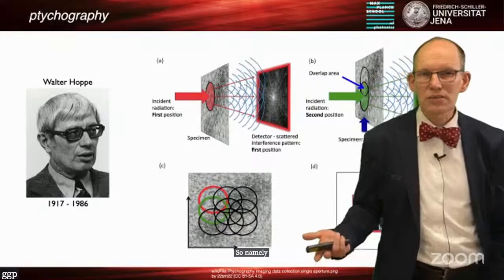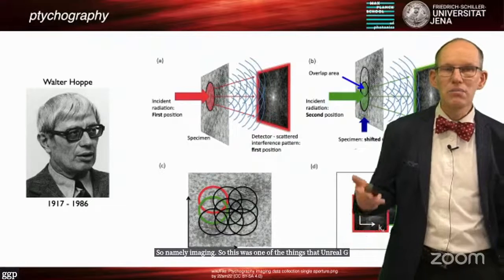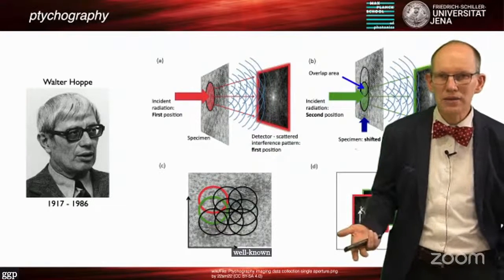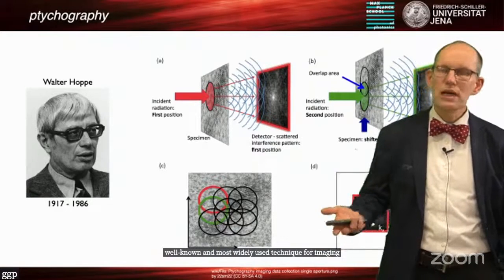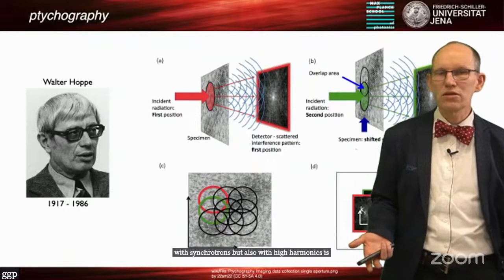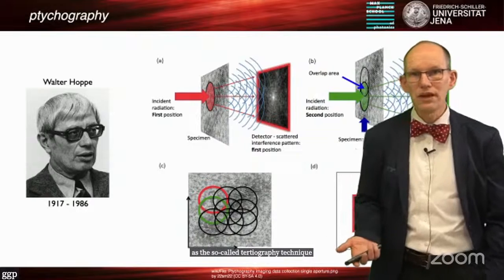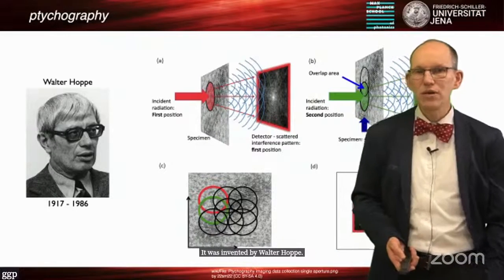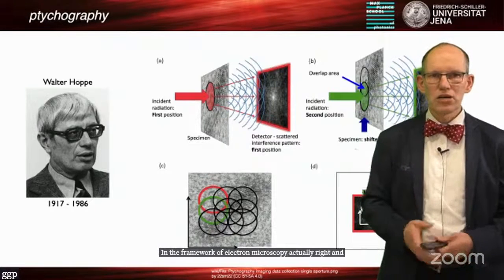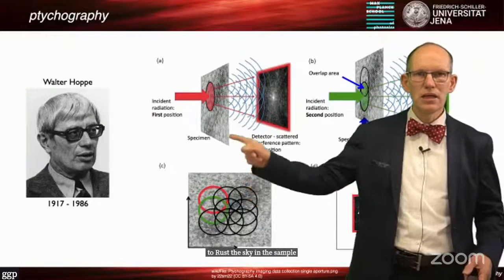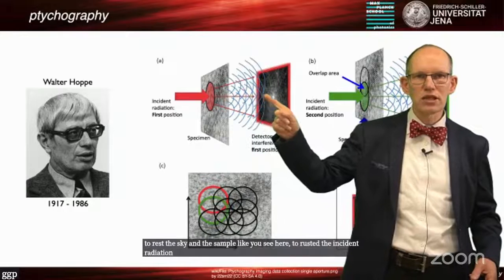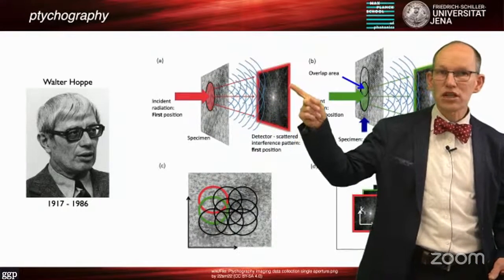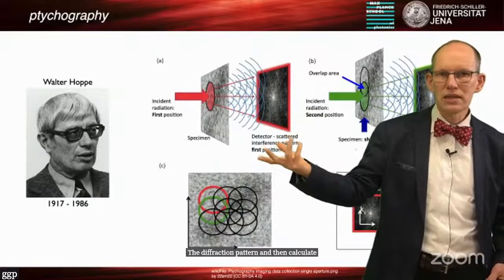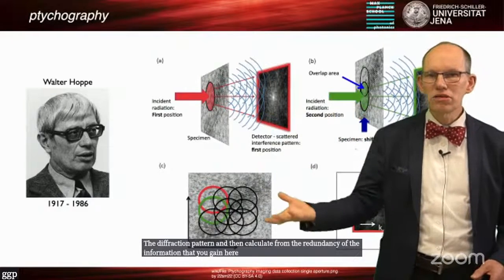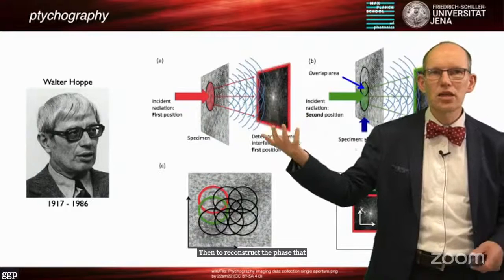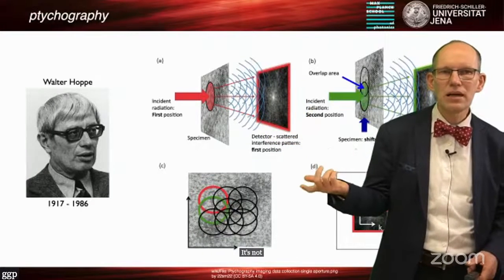Okay, using high harmonics for something different than attosecond pulse generation, namely imaging. So this was one of the things that Anne L'Huillier referred to. And the most well-known and most widely used technique for imaging with synchrotrons, but also with high harmonics, is the so-called ptychography technique. It was invented by Walter Hoppe in the framework of electron microscopy, actually, right? And the idea is to raster scan the sample like you see here, so to raster the incident radiation at different positions and to record the diffraction pattern, and then calculate from the redundancy of the information that you gain here to reconstruct the phase that is initially thought to be lost. It's not entirely lost. It can be reconstructed.